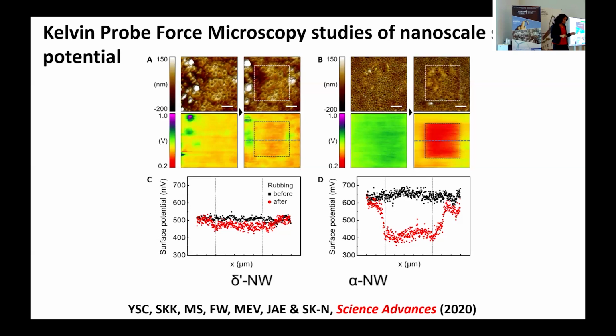So in the case of a triboelectric material, the property that we're most interested in is the surface charge, right? The higher the surface potential, the more the surface charge, the more likely it is to generate or to transfer this during a rubbing event. So in this case, we use what's called Kelvin probe force microscopy, which allows us to map the surface potential of these materials. So here are two examples.